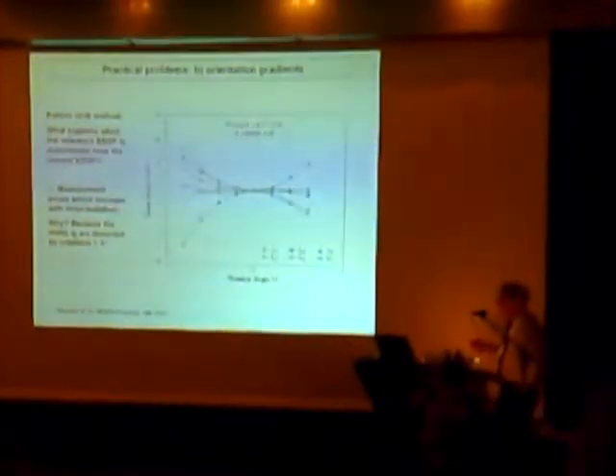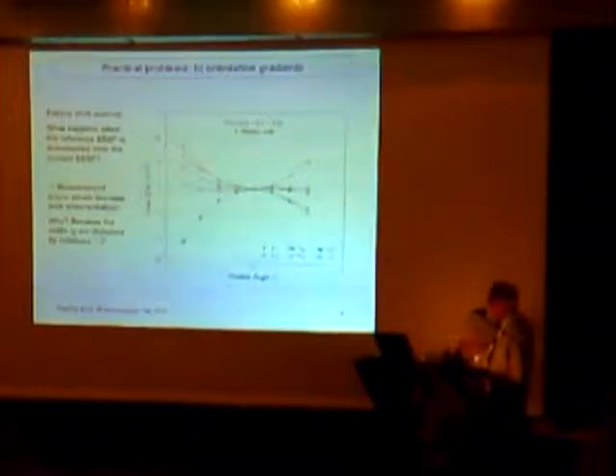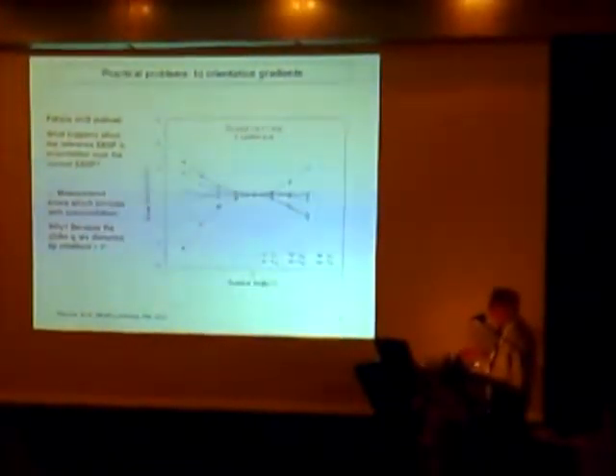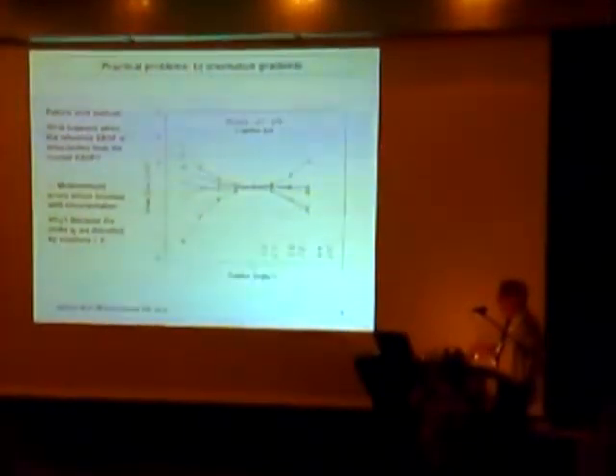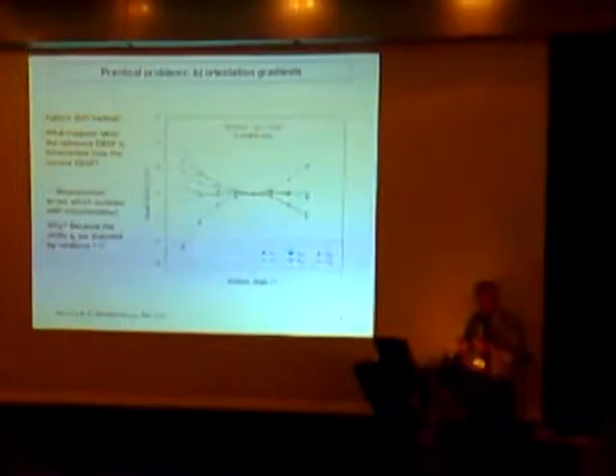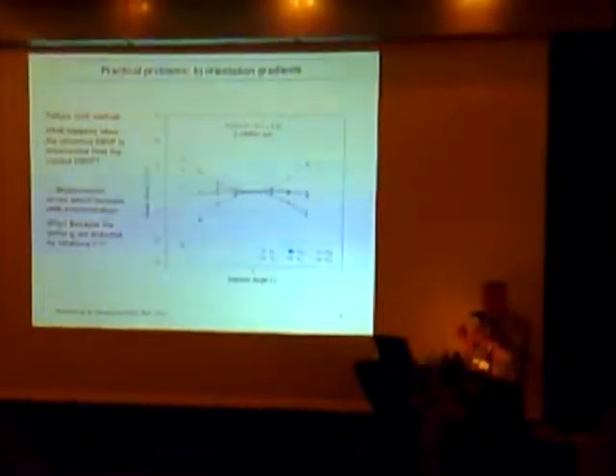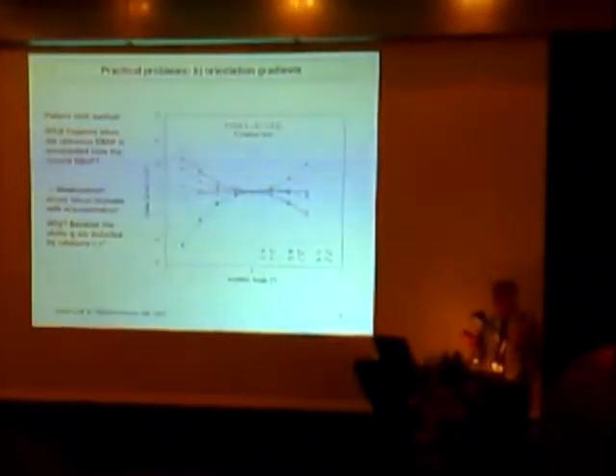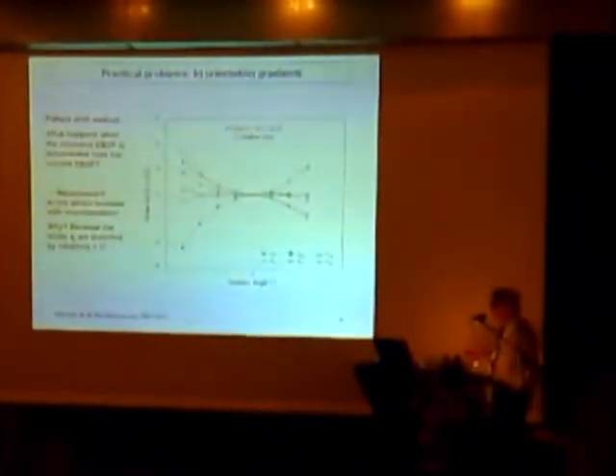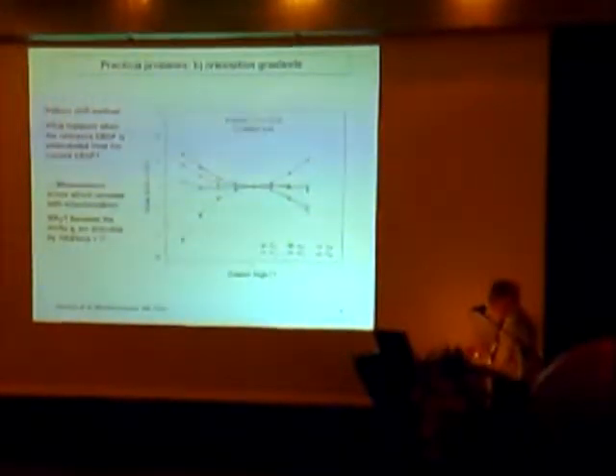And this was work that Claire did, looking at the influence of what happens when the reference EBSP is misoriented from the current EBSP. Using simulated patterns, you can use a numerically simulated pattern, so you know all the exact orientation, the strain, the shapes, you know everything. You could compare it then with what your cross-correlation method would give. And this, in fact, shows that if you have a rotation angle, here we're looking at the error which is induced by rotations between the reference and the current pattern.